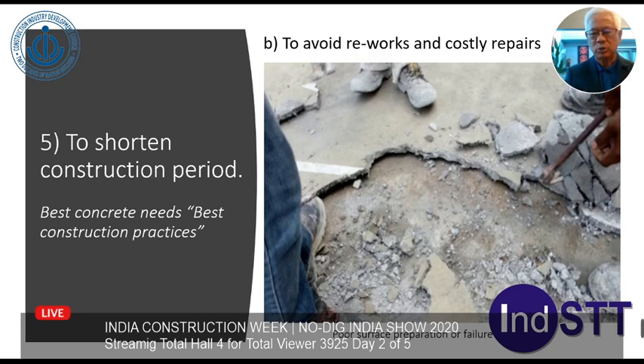As you know very well, when it dries up, you have to put another coat of bonding agent, unless there are some specific bonding agents where you must let it dry before you put your concrete on top of it. So imagine if this failed, you have to hack everything out and redo it, and it costs you a lot of money. Especially doing thin concrete topping is very, very difficult if you don't understand it. Most of the time, it will end up with a lot of delaminations. So this is the reason why you make sure that you follow all the good construction practices.